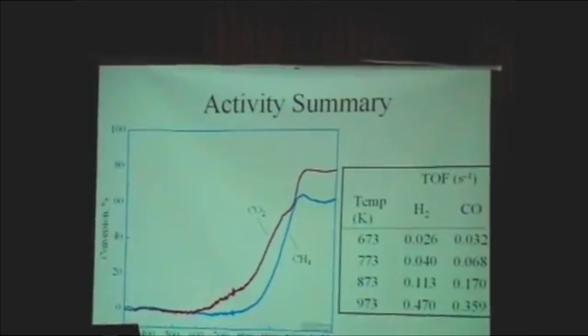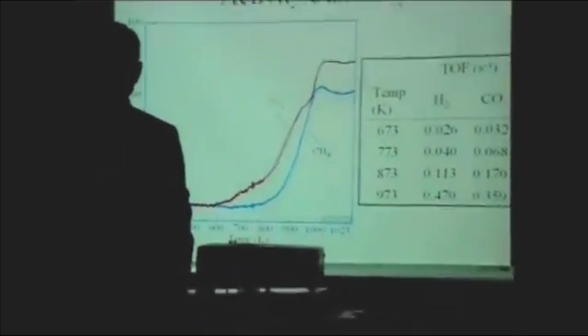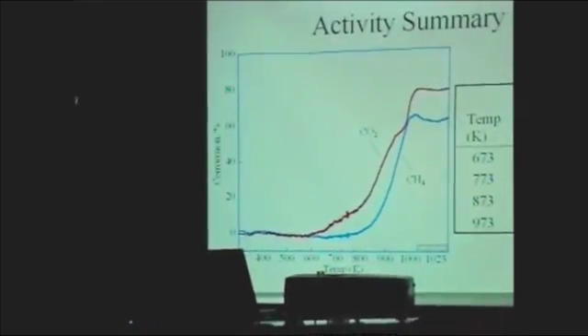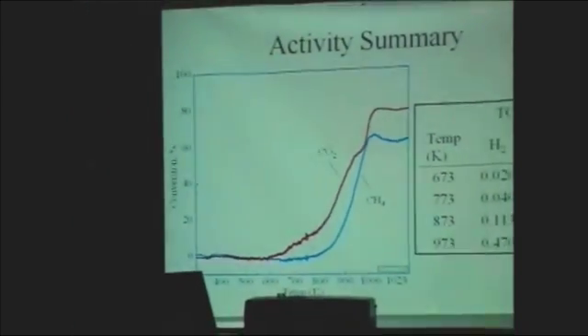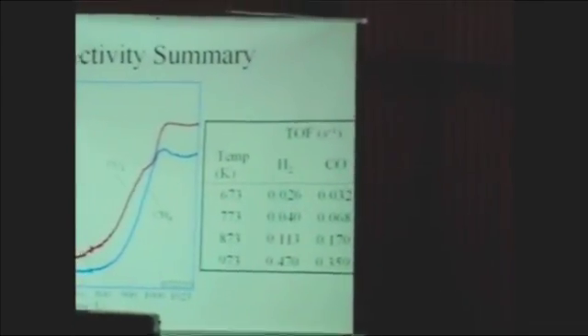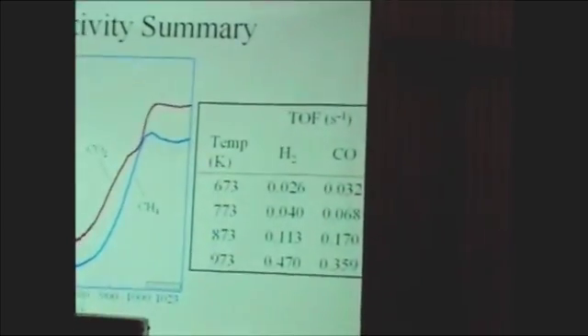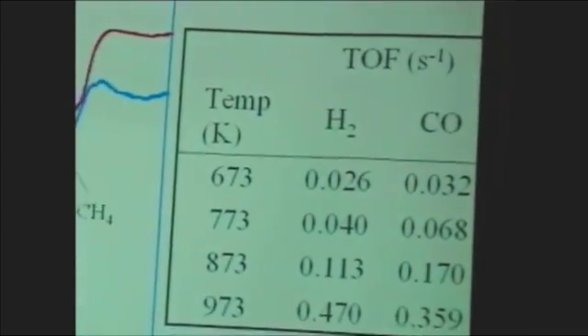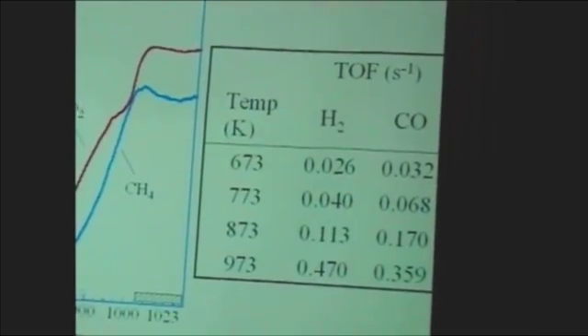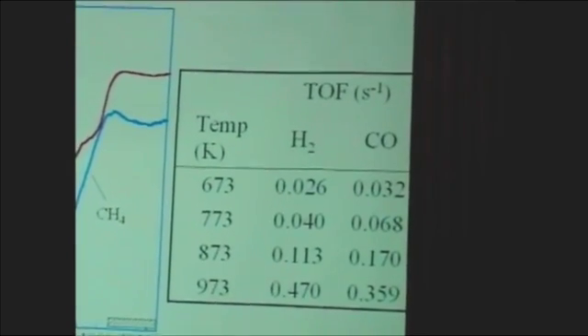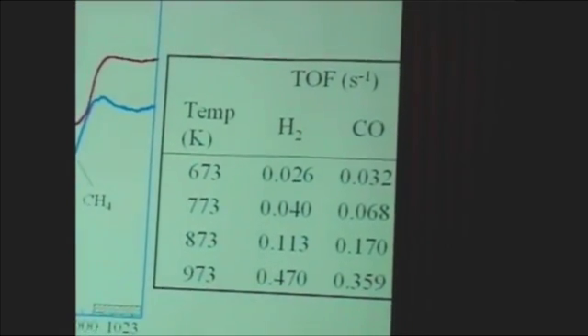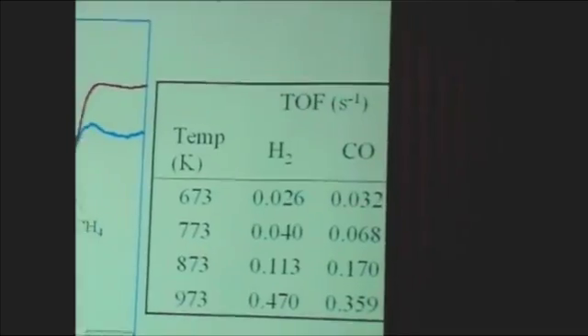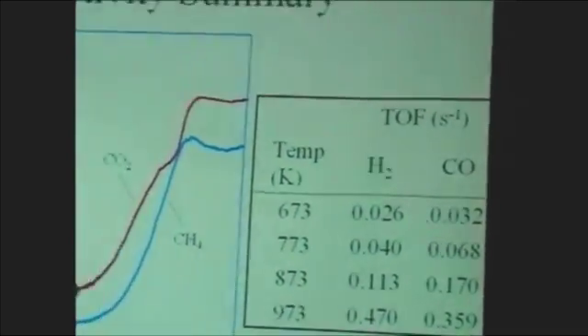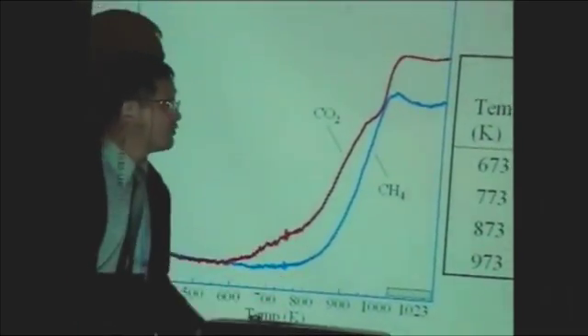So this is the result of the reforming reaction of CO2 and methane over a catalyst supported on alumina. The weight percentage of loading on the catalyst is about 4% here. So we heated up the reactor, and this is simply the product of conversion of CO2 and methane. Converting the CO2 and methane is not usually one-to-one, simply because the reverse water gas shift reaction is involved.